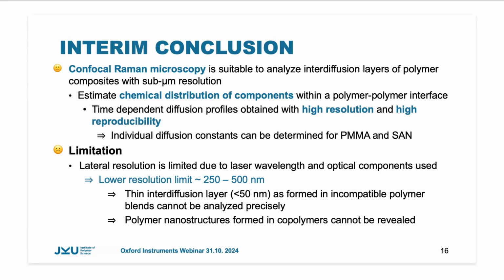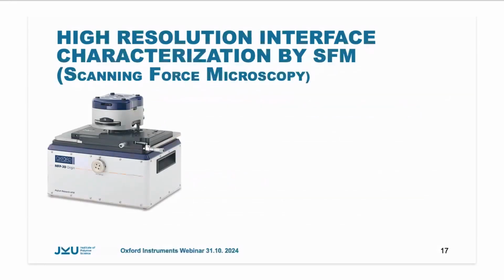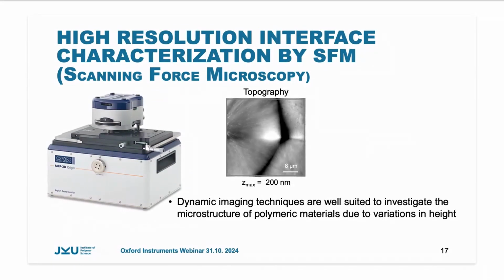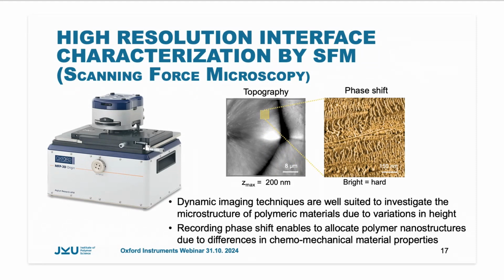And what we are not able to elucidate are differences in the polymer structure. Therefore, it seemed to be a good idea to use a second technique as a complement. We chose scanning force microscopy as a complementary technique because we can apply dynamic imaging techniques to investigate the microstructure of polymeric material due to the variations in the sample height, as shown here in a topography image of a polypropylene spherulite. And when we additionally record phase shift images, we can allocate polymer nanostructures due to differences in the chemomechanical material properties. So we can highlight here crystalline lamellar structures. Let's see how this technique performs.